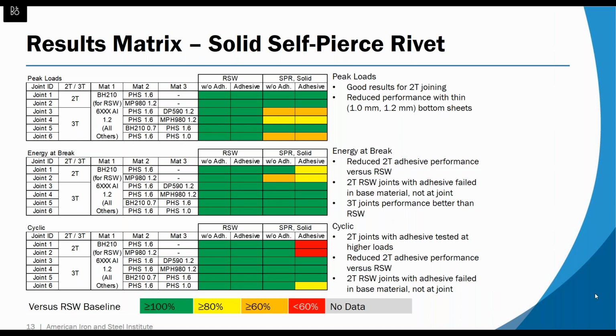We saw more variable performance in the 3 thickness joints, and it was really sensitive to the bottom layer thickness. In the thinner materials, in the 1 and 1.2 millimeter range, we saw some reduced strength performance, but in the relatively thick 1.6, it was comparable to the resistance spot weld.